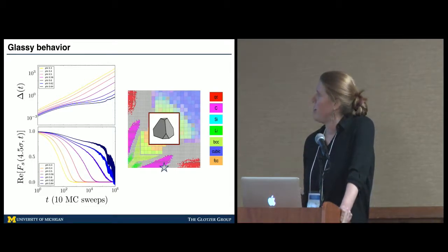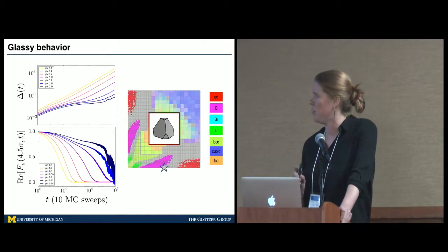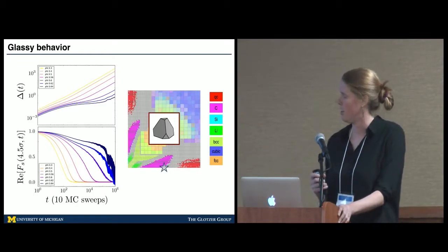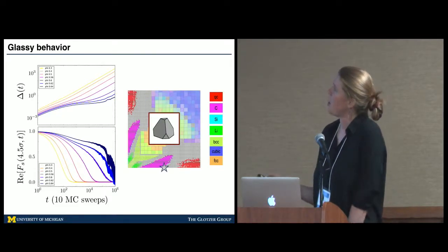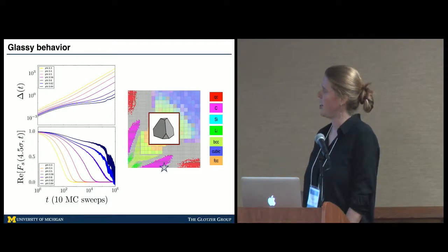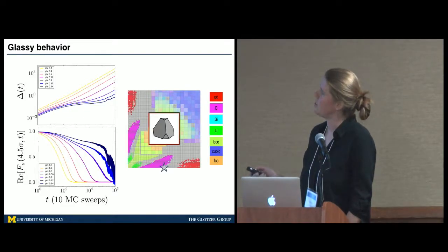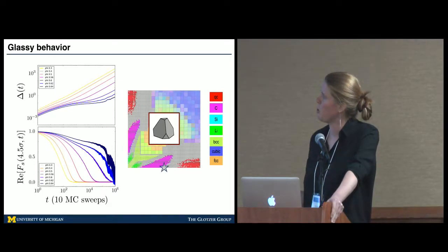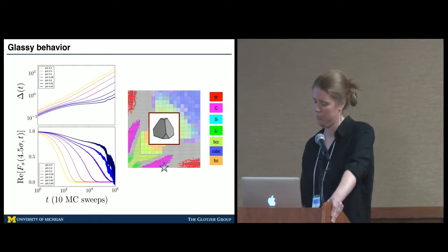So when we ran our simulations, I should say also, we actually just used one GPU per simulation on Blue Waters because we decided that was the most efficient use of our allocation. But it was still very parallel because of HOOMD's parallelization. When we used HOOMD to do these simulations, we saw this caging behavior in our sample state points. So here the curves are more blue as the system density increases. And so you can see that this caging becomes more and more prominent as the system density increases. So this is somewhat verifying the glassy nature of our hard particle model.